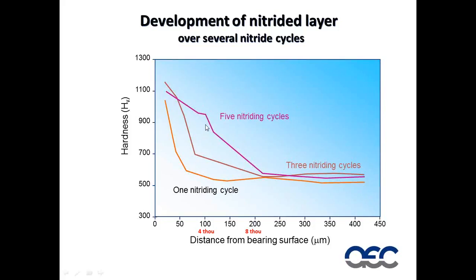The other thing is, it's always been my approach that I don't take a given number of billets between nitridings. I take a given distance, be it in feet, meters, miles, or whatever you want, of extruded product. Because if you're making a 1-inch round bar, you extrude very little round bar for quite a few billets. Whereas if you're making a 40 thou thick small glazing clip for windows, you extrude an enormous distance of material running at speed over the bearings. So I always use distance as the guide to my nitriding cycles.